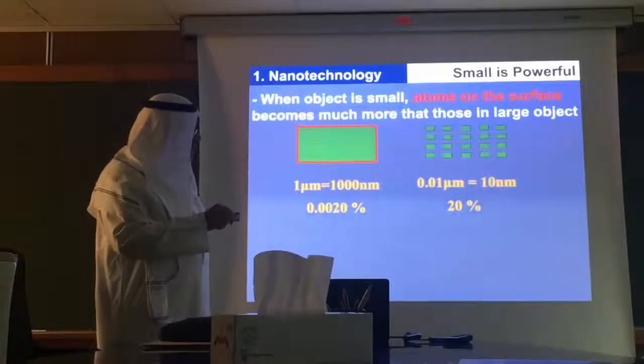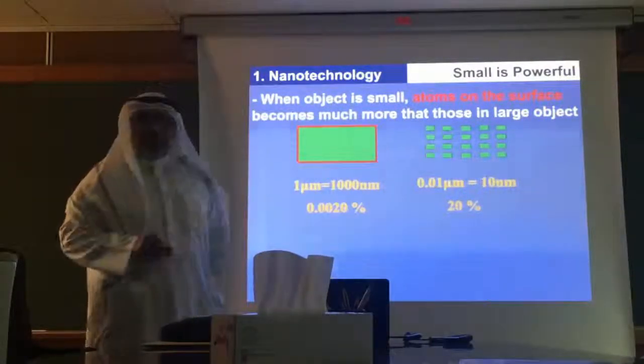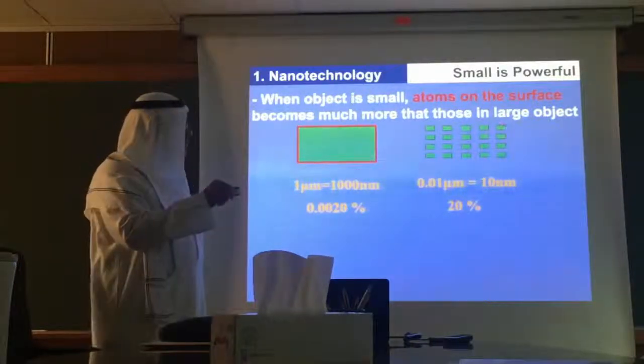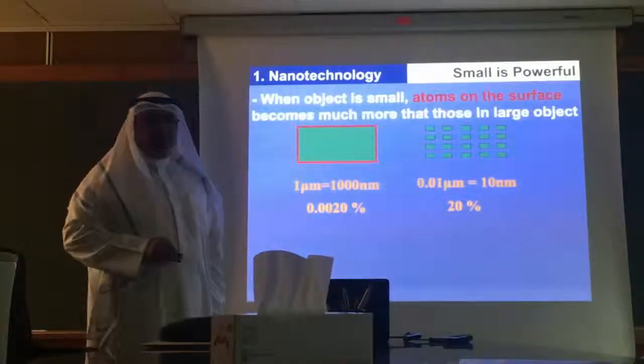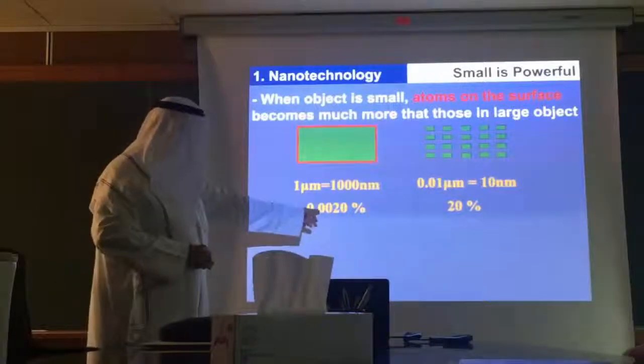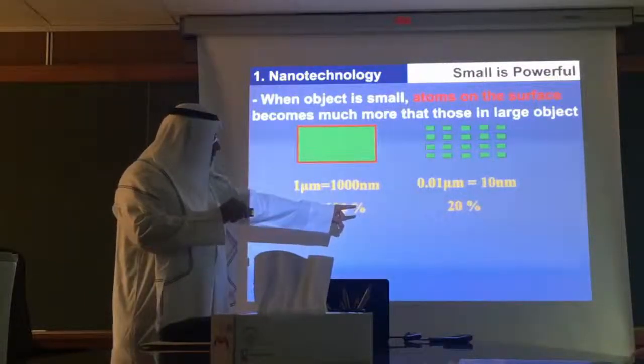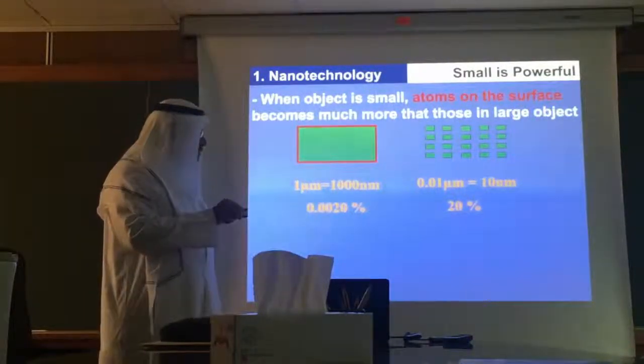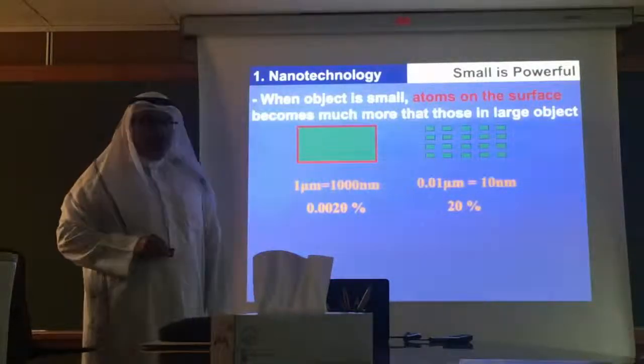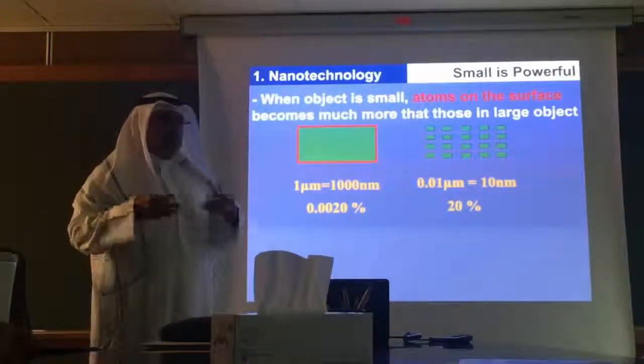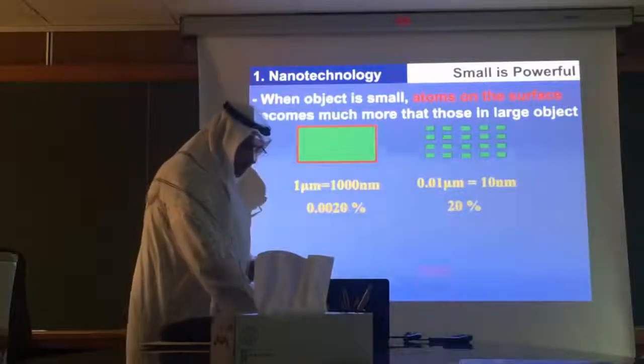Now, if you make it 0.01 micrometer, we are in the nano size, 10 nanometers. We are exposing 20% of the material. 20% of the material will be on the surface, and 80% will be in the bulk. So you can see, from 20 to 0.002 is 10,000 times. You are enhancing it 10,000 times.